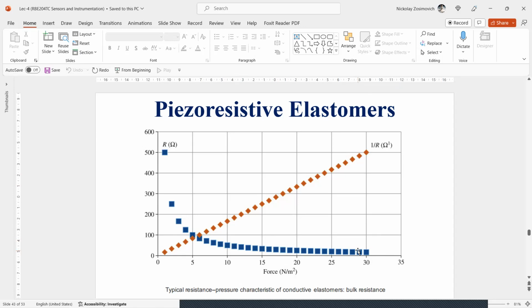And here on this diagram, the blue squares present a typical resistance-pressure characteristic, revealing that piezoresistive sensors are very sensitive, because the resistance may change several orders of magnitude, but highly nonlinear, as you can see here. Only one part you may see as linear, but generally not. And the initial force is very, very nonlinear. The same figure shows the conductance, 1 over R, which has an almost linear relation with the pressure, on the red diamonds. A suitable way of creating this reciprocal value is by using a standard inverting amplifier.